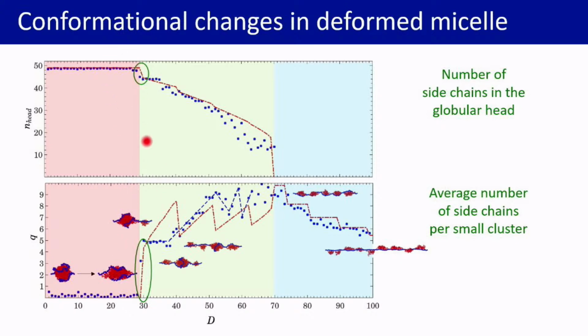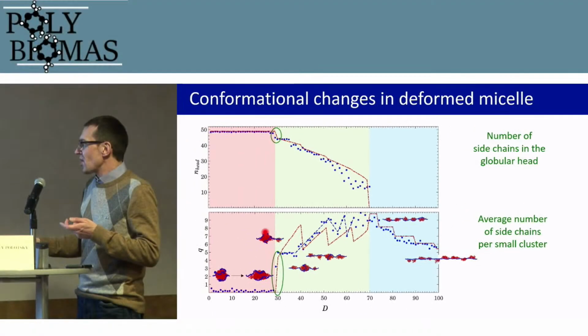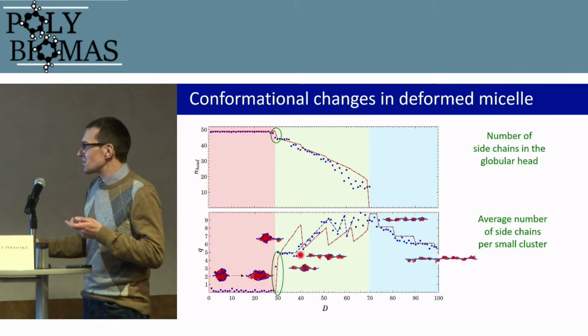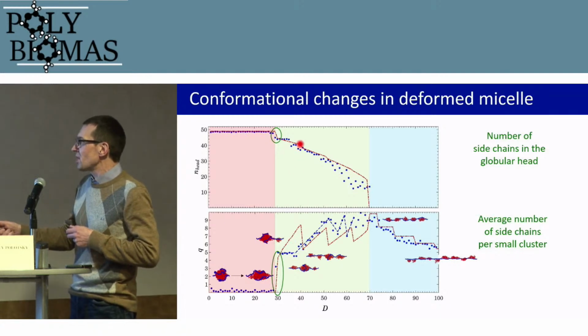So we see that in the first regime there is only a big head and no small cluster, then a first small cluster forms. It already has an aggregation number of about 4 or 5, and with a following increase in the distance between the chain ends, the aggregation number of the cluster continuously increases, and the number of side chains in the globular head continuously decreases, which means that upon extension, side chains continuously, one by one, leave the big head and join the small cluster. But at some point, the system decides, so to say, to form the second cluster and redistribute the material between two clusters, and this is accompanied by a jump in the average aggregation number per cluster, and a small jump in the number of side chains in the globular head.